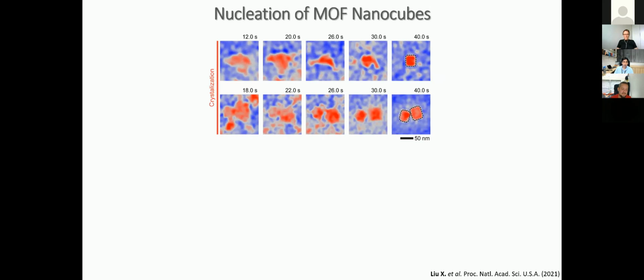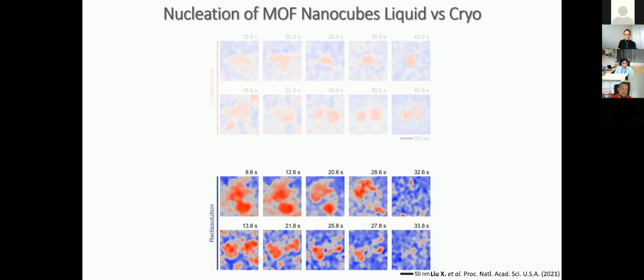So here is the nucleation event, right? You have a solution which is phase separating, slowly condensing and collapsing into the nanocubes, right? Again, here you have this collapsing into these crystal nanocubes. But is this the thing that always happens? And the answer is no, right? Sometimes you form the dense regions, they attempt to collapse, but then they dissolve into the solution. So cryo would not tell you, right?